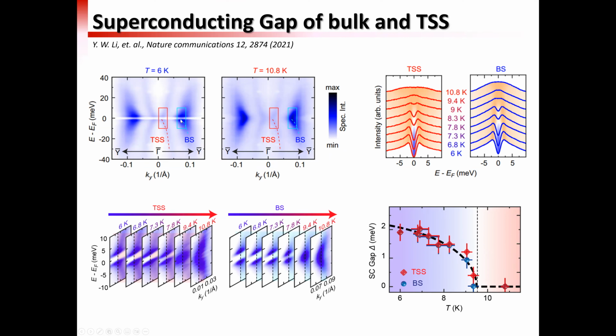And we can see that here we have both the bulk states and the surface state dispersion. Both of them were gapped below the superconducting transition temperature. You can see this transition more clearly from the momentum distribution curves on the right-hand side. At 10.8 K, there's no gap, and when we decrease the temperature, the gap starts to show and gets more and more prominent at 6 Kelvin. Here we separate out the dispersion of the topological surface state and the bulk state, and you can see clearly how this gap closes upon the temperature rising.